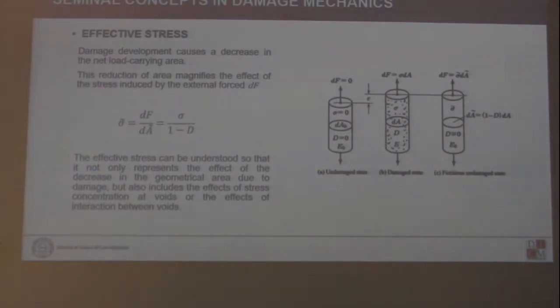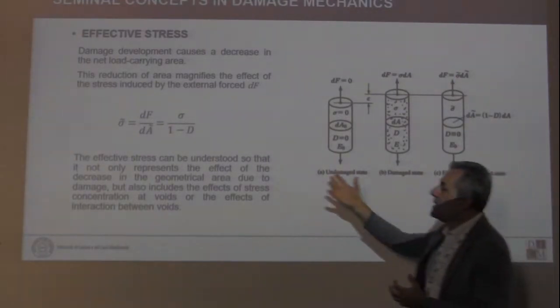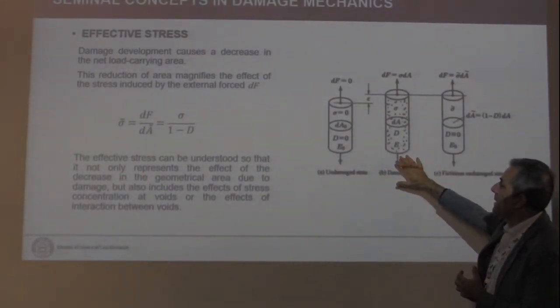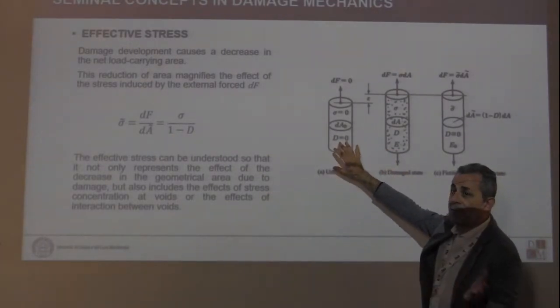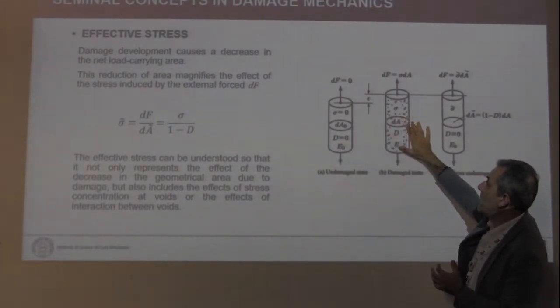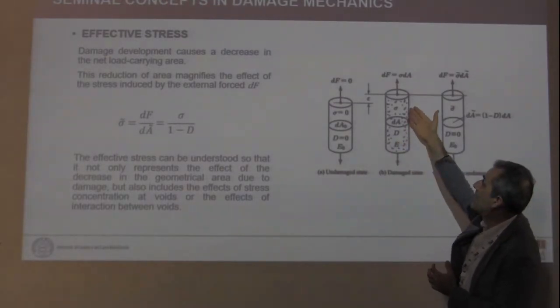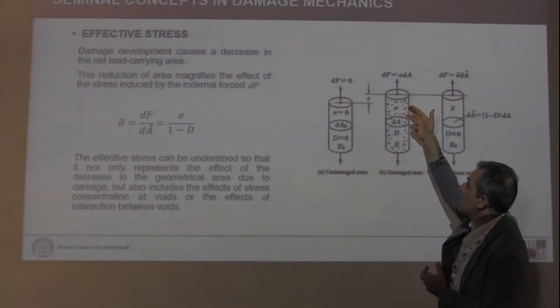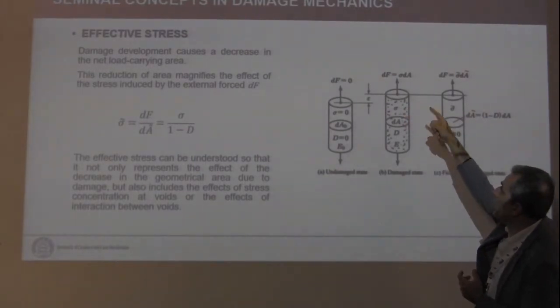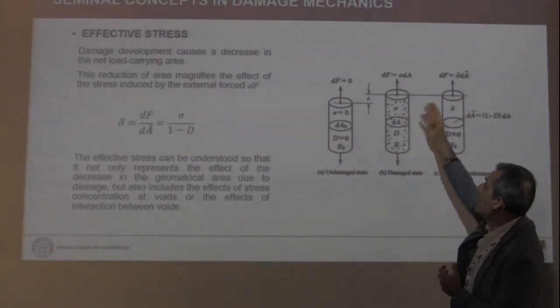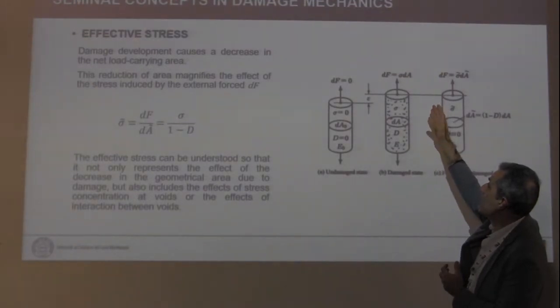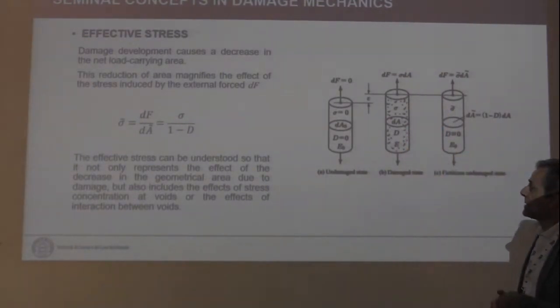Another seminal concept in damage mechanics is the concept of the effective stress. So the effective stress is a concept that is derived from this approach, in which we say that if we have some damage, we can deal with a material, this is the virgin material, where we have no damage. If there is damage, we have a distributed damage under stress sigma. Under a force F, the force is sigma times dA, where dA is the effective net resisting area.